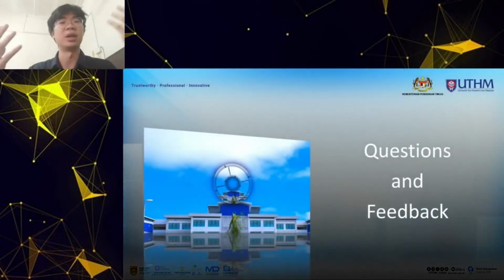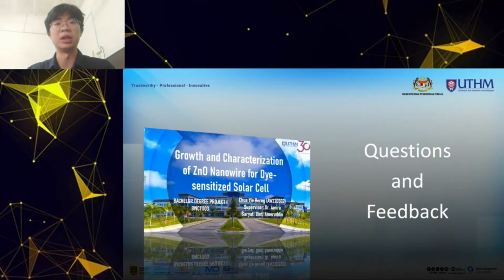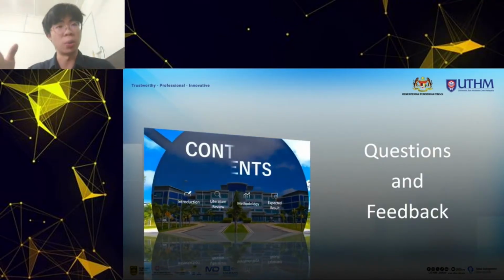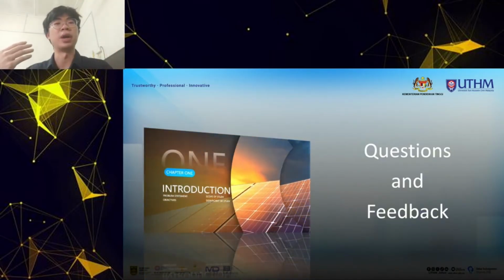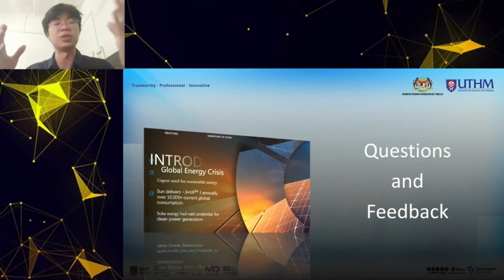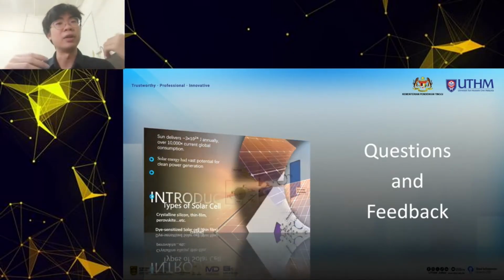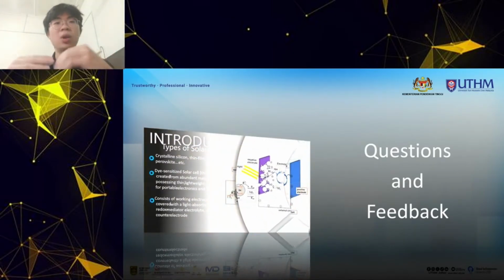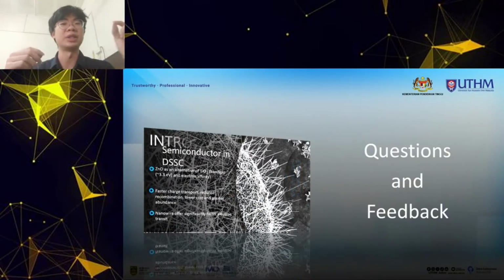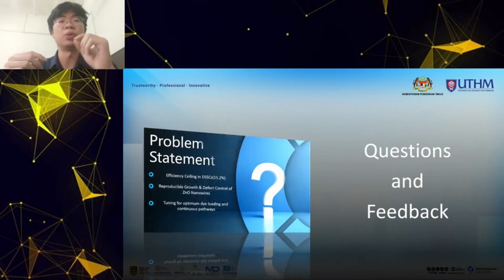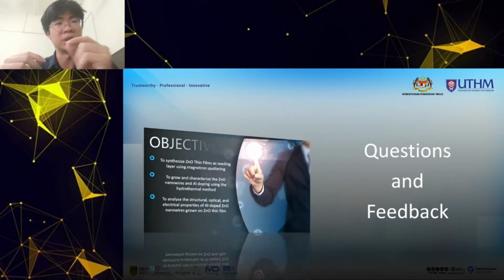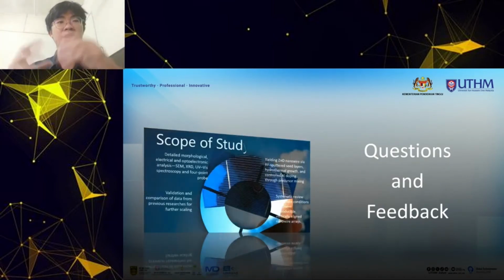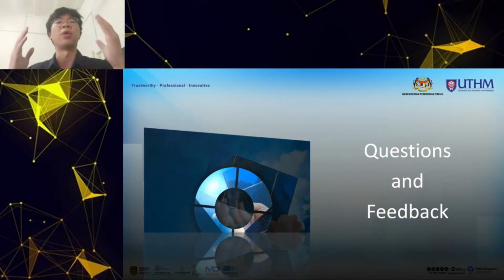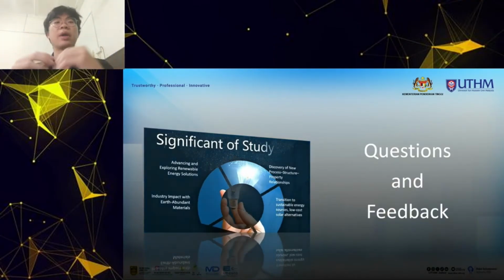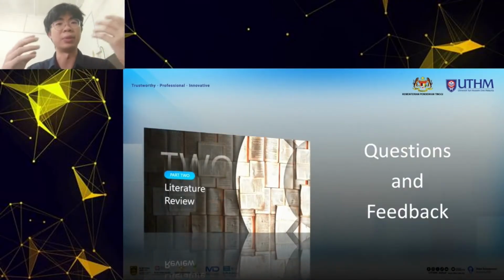So, as a conclusion, this presentation outlines a comprehensive plan to develop and characterize vertically aligned aluminium doped zinc oxide nanowire for use as a transparent conductive photoanode in a dye-sensitized solar cell. By combining RF sputtering of zinc oxide seed layer with low temperature hydrothermal growth and precise tuning of aluminium doping between 0.9 to 1.2 atomic percentage, this study will establish a reproducible synthesis protocol for high-quality zinc oxide nanowire with controlled morphology and alignment.